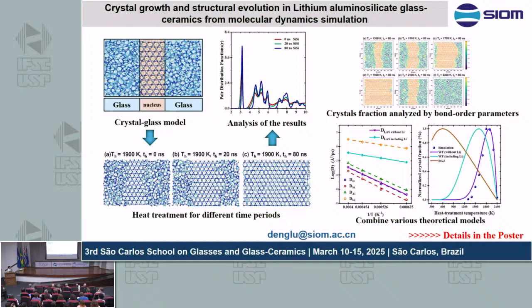We put the nuclei in the system and heat treated it for different time periods or different temperatures. The crystal fraction is analyzed by the bond order parameters, and then finally we combine various theoretical models with the MD results. The details are shown in the poster, and if you have any question, you can contact us by email.